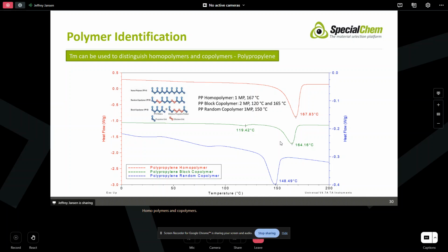In the same way with homopolymers and copolymers, we have polypropylene, okay? With polypropylene, it comes in a variety of different configurations, a homopolymer, a block copolymer, a random copolymer. And by the melting point, we can look at those materials and see what's going on. For example, the homopolymer is going to have the highest melting point, almost approaching 170, and it's a single endotherm. The block copolymer is going to have blocks of propylene, but also some blocks of ethylene. And those ethylene segments are also going to melt. And so we've got a melting point around 119, representing the ethylene functionality, and a little bit of reduction closer to 165 for the propylene segment. Okay. And then if we've got a random copolymer, that melting point shifts because of the disruption in how those crystals form because of the ethylene and propylene mixed together randomly, and that melting point is drastically reduced. Again, very useful for being able to identify that where FTIR is not going to be helpful.